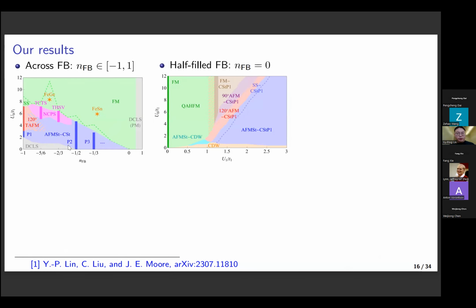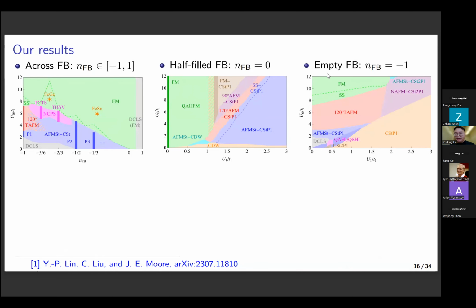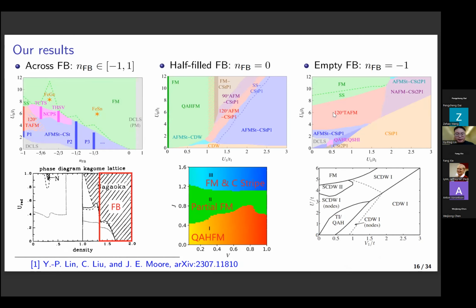Secondly, we also add the extended repulsion to the model so that we can see some additional orders from the original phase diagram here. And thirdly, we have revisited the empty flatband, and we see that the non-collinear order, like 120-degree antiferromagnetism, is actually very important. You can see a brief comparison with the previous analysis. For example, for the cross-flatband phase diagram, we see a lot of new phases here, which occupy roughly this regime. And for the half-filled flatband, we're extending the original phase regime to see a lot of new phases here. And for the empty flatband, we are seeing the importance of the 120-degree order in this regime.